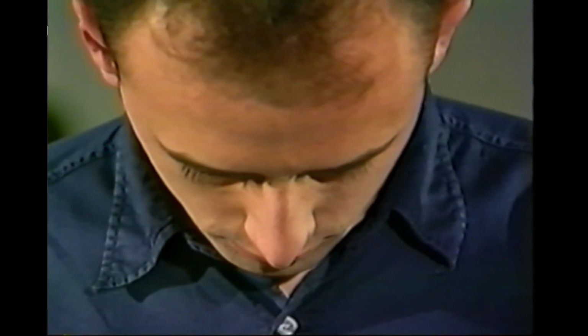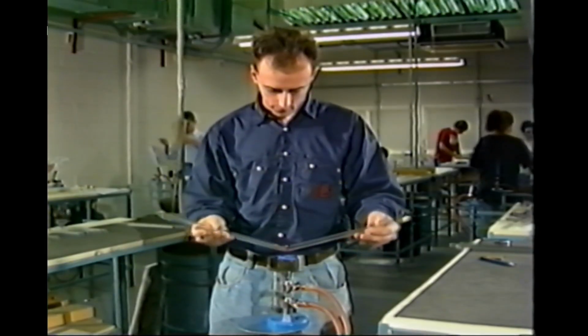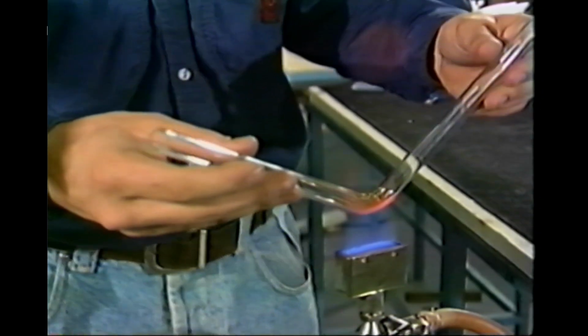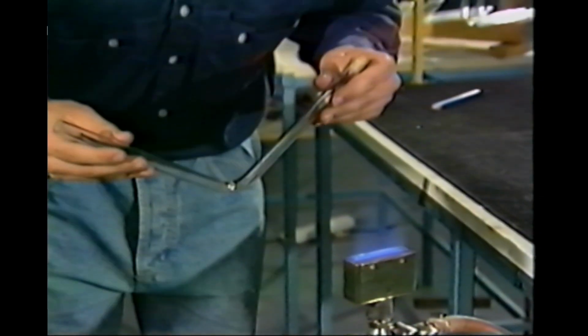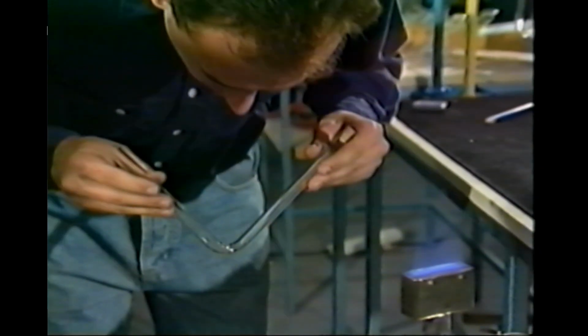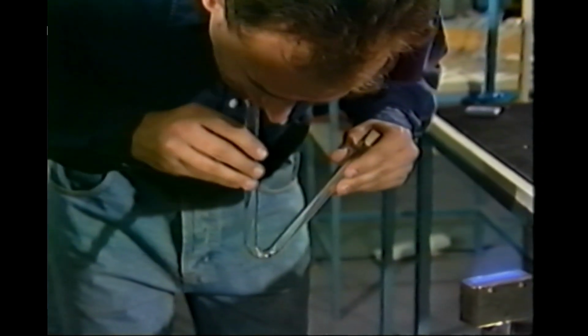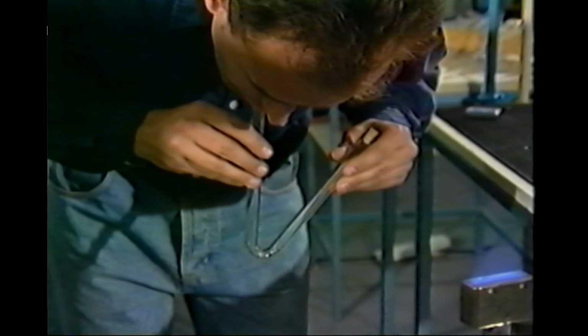When sufficient extra melting and the pre-shape have been completed, bring the glass towards you out of the flame and down to waist level, ensuring that the 45-degree angle of both side arms is maintained and the mark is directly at the top. Lean forward slightly from the waist, bringing the head in line with and above the central pencil mark. While maintaining the 45-degree angle on the sidearm held stationary in the left hand, shape the right hand until the sidearm is vertical and directly in line with the mouth, ready for blowing.